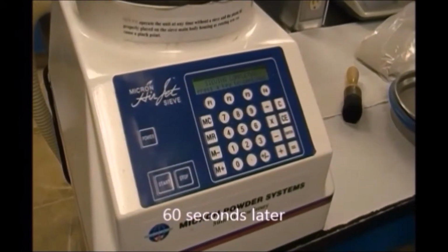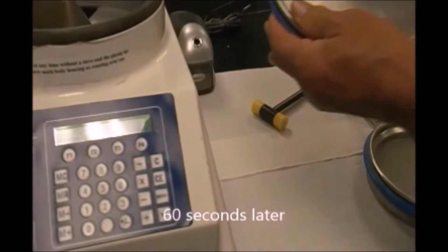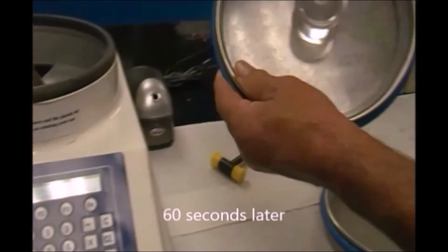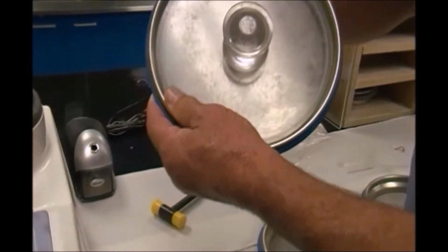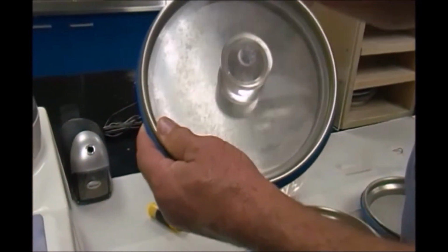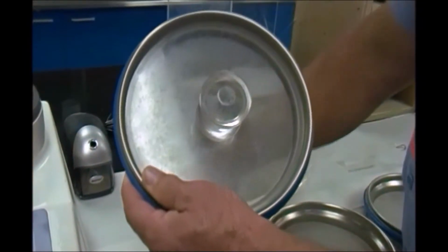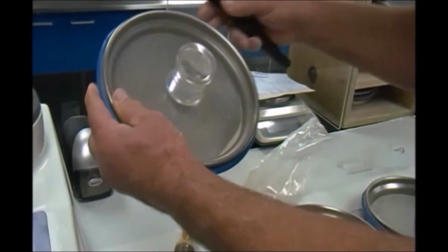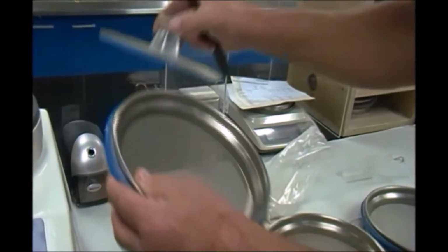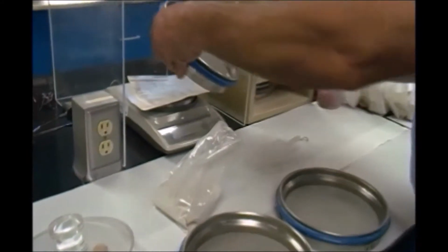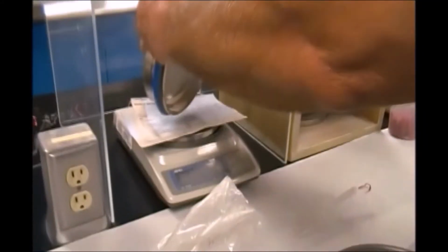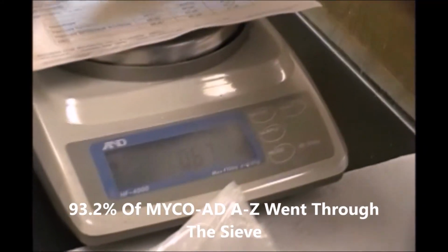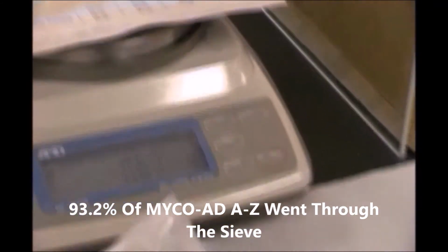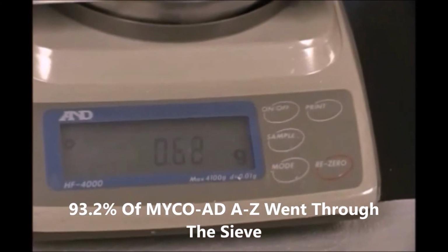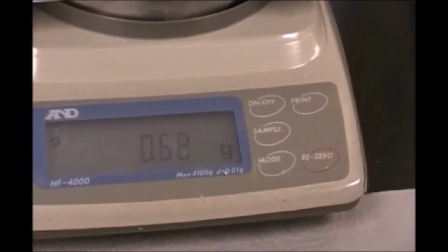After 60 seconds have passed, the sieve mesh screen will be removed from the Micron powder machine. We will use a small brush along the backside to brush off any product that went through the sieve but may still be on the screen. The product will then be weighed again. You will see that out of the 10 grams of product, only 0.68 grams remain, meaning that 93.2% of the product went through the sieve.